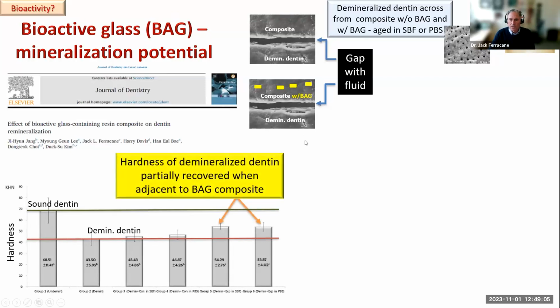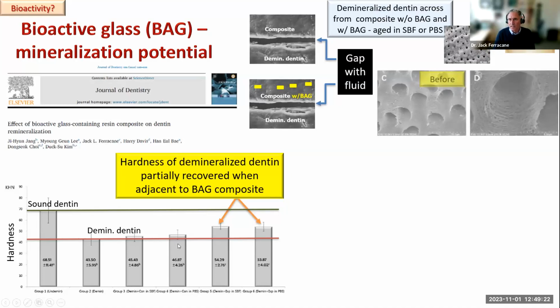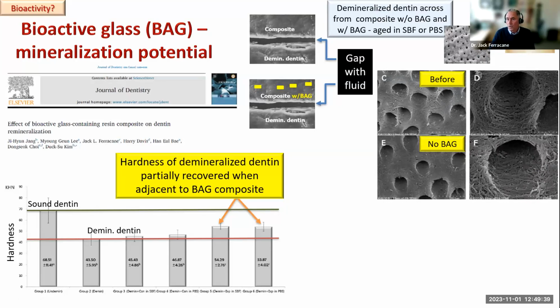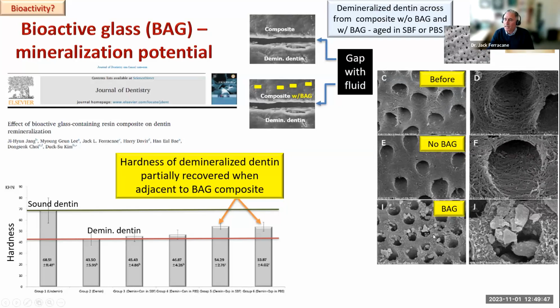And then after the experiment, measuring the dentin that had been exposed to the composite with the bioactive glass, we found that almost 40% or so of the loss of hardness had been recovered when adjacent to the composite with the bioactive glass, but not to the composite which did not have the glass. And if we look at this from an electron microscope view at relatively lower and higher magnification, we see the dentin surface before, with the demineralized tubules. When it's exposed to a composite that did not contain the bioactive glass, it looks very much the same. And then when it was exposed to the composite containing the bioactive glass, we see this deposition of mineral all along the surface within the tubules, et cetera, which would help to account for this recovery. Now, it's not perfect remineralization of dentin, but it is mineral formation, which produces this recovery of hardness.